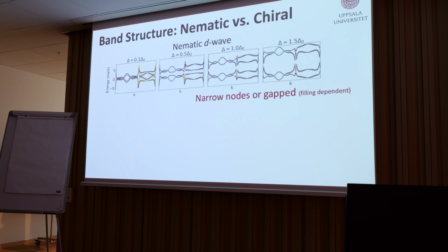Then we looked a little bit more at the band structure, because I haven't actually talked to you about the structure of the nematic state. So here I plot the band structure along some high symmetry lines in the Brillouin zone for increasing order parameters. So these are reasonably big order parameters. We're trying to just illustrate what happens. And you see, as I crank up the order parameter, the spectrum gets more and more gapped.